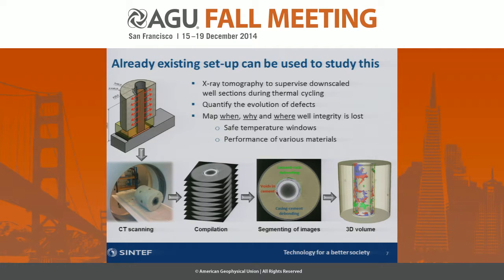And then what we're actually measuring is that we're scanning these samples in a medical CT, and again looking at how defects in the cement, for example the cement-rock debonding, voids in cement, or casing-cement debonding, are evolving with time. So here you see a typical sample before any thermal cycling, showing that it's very difficult to get a really good cement job, even in the laboratory. It looks a little bit worse than it is. The blue here is debonding between casing and cement, and the green is between rock and cement. And this is even before any cycling.